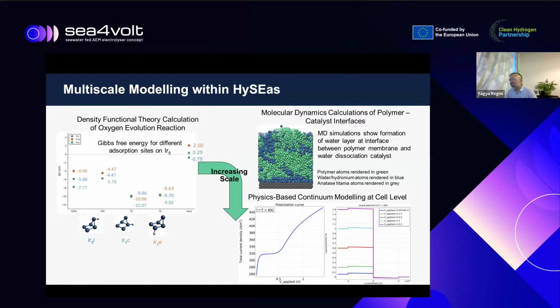From that atomic scale, we go all the way to centimeter or meter scale, at least in theory, and we look at what happens, on the right hand side, to the water as it approaches, let's say, the electrified interface between your catalyst, membrane, and your transport layers. So we're guided by computational models so that we have a feedback into our experiments too. For example, the computational model guides us how thick the TiO2 layer between the PEM and AEM needs to be.